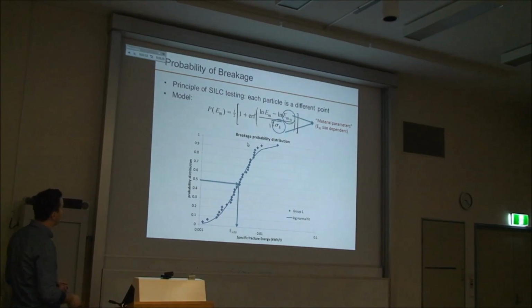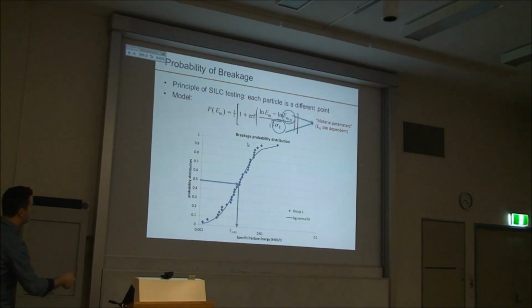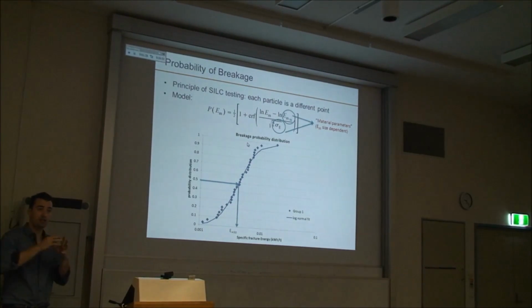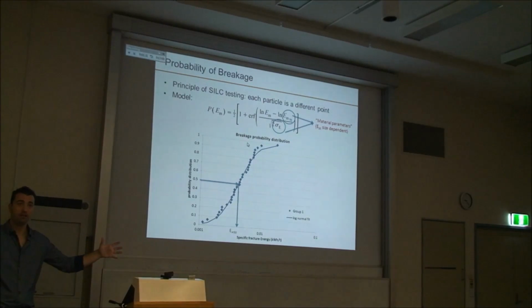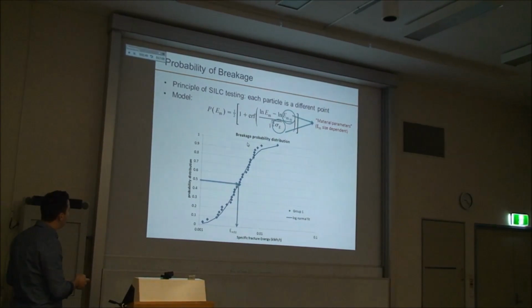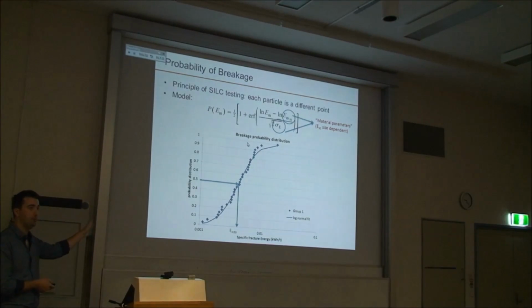The line that you can see here on the graph is actually a model that was derived a long time ago and has two parameters. First one is the E50 and the second one is the geometric variance of the distribution, which is basically saying how much this curve is spread. If this number is higher, the curve is going to spread, so highly variable ore. There's a lot of different strength in the ore. If this number is small, then the curve is going to be sharp and there's not a lot of variation, or variability, in the ore. This probability distribution can be observed for all the parameters: the stiffness, the strength, the fracture force, and the fracture energy. All the four parameters can be plotted this way.